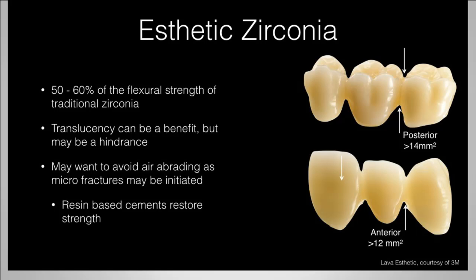Dr. John Burgess at the University of Alabama is one of the researchers I trust wholeheartedly. In his lab, what they're starting to find is, if you air abrade translucent zirconia, you will cause microfractures. If microfractures occur, the ceramic is much more weakened. It does not have that toughening phase like traditional zirconias have. So it is imperative that if we use aesthetic zirconias today, or translucent zirconias, we strongly consider using a resin-based cement. At the minimum, a self-adhesive resin should be used with these materials.